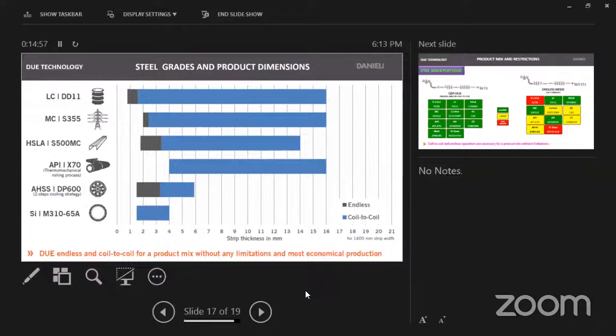Because when the slab is coming from casting, the slab inner structure is a little bit coarse, and when it enters the roughing mill, after roughing it takes some shape. But after that, you have to give some open space to make the structure homogeneous. And after that, you have to put it in the finishing mill. Otherwise, you will not get proper quality of API grade. So in conventional thick slab casting and rolling, the conventional hot strip mill can produce these API grades, because there is a gap, which we call the delay table, between the roughing mill and the finishing mill.